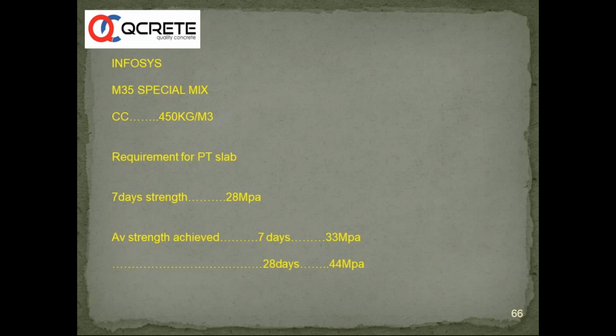We can design the mix, controlling the water cement ratio with good admixtures, where we can get 7-day strength required for a PT slab. The only important point here is if we don't get this info, some customers are there who don't talk about the 7-day strength. Then they will say we have used this for PT slab. Then it will be a problem actually. So if we don't get information, we cannot make concrete as per requirements. So if we get the requirements from customers, we can make proper concrete with fly ash, and tailor-made concrete we can give.